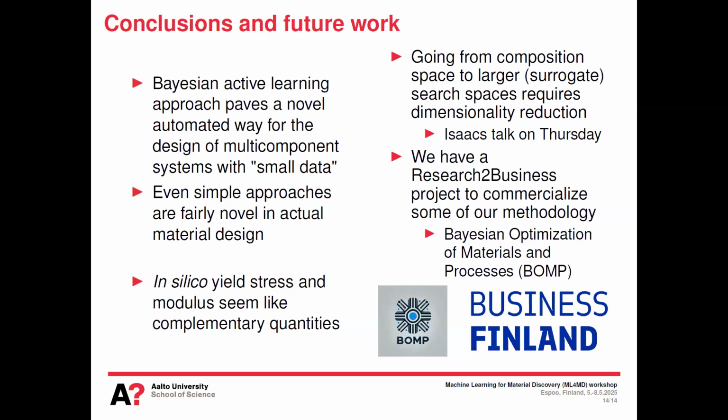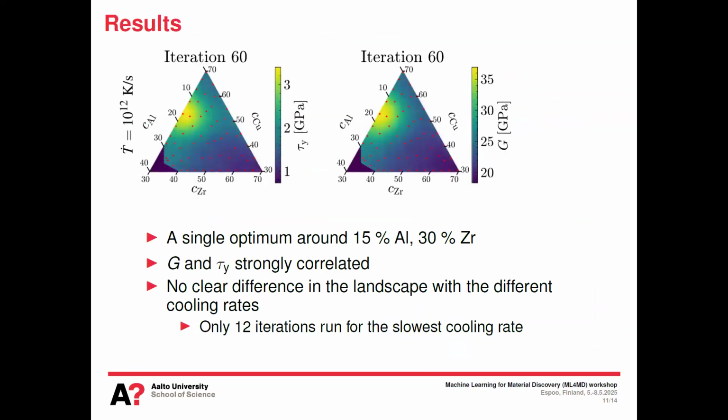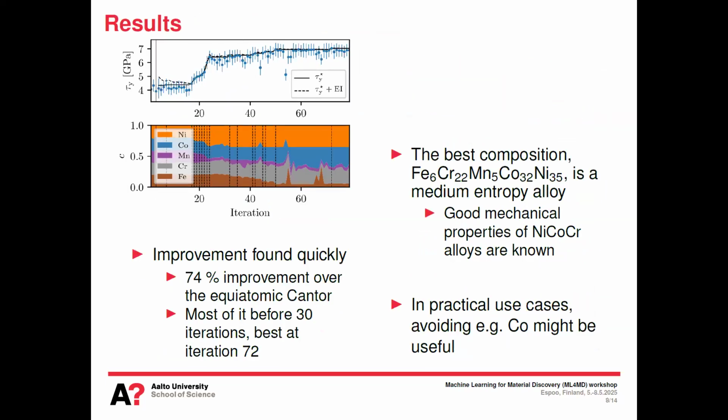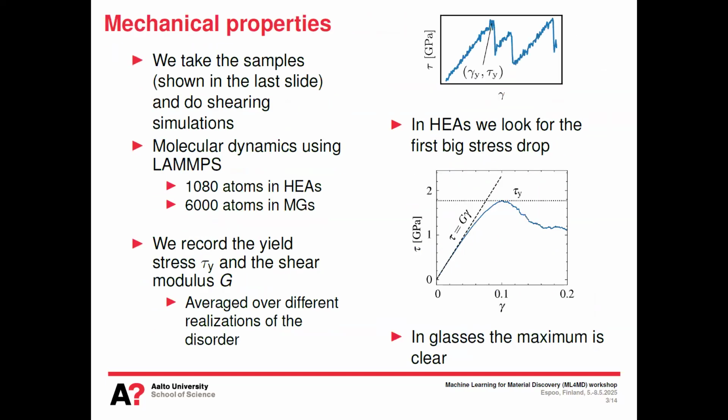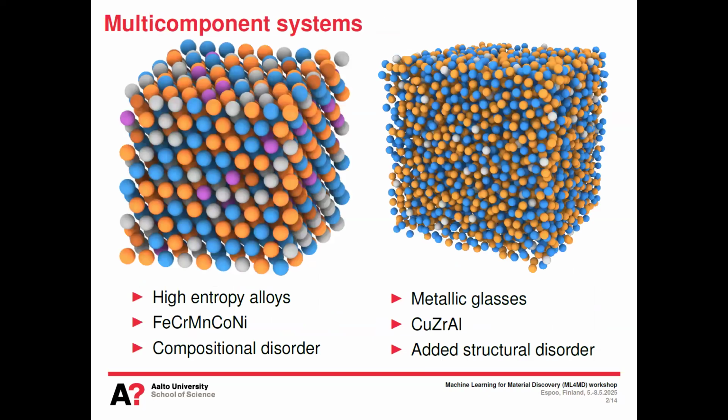On the metallic glass project, I have a question about whether you considered if the thing is actually likely to form a glass. Because in simulation, it's hard to crystallize from the melt since you're cooling at 1,000 billion Kelvin a second, and to form a glass in an experiment, you're looking at 10,000 Kelvin a second cooling rate.